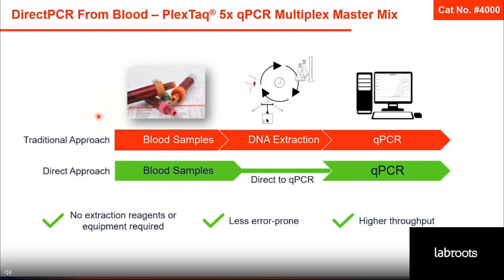So in a traditional approach, using traditional products, one would have to take a blood sample and then subject it to DNA extraction and purification. And then this sample could be used for qPCR analysis. When you're using PlexTaq, you can use blood sample directly in the qPCR reaction. So there are no extraction reagents required, no equipment required for DNA extraction. So this is, of course, less error prone, and at the end you get much more starting sample.